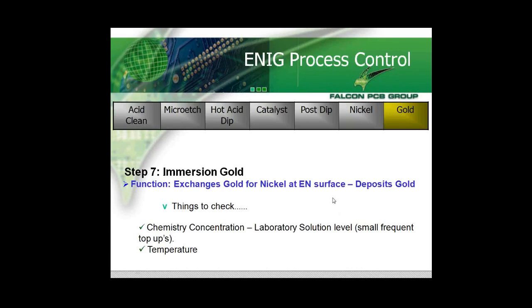Immersion gold again runs hot but doesn't create too many problems. Mainly the standard laboratory solution checks, but nowhere near, of course, as problematic as the electroless nickel. Most important thing for the immersion gold, again as stressed by Nigel, is not to leave the panels in too long. You don't want to get too thick a gold deposit on, otherwise you get too much hypercorrosion.